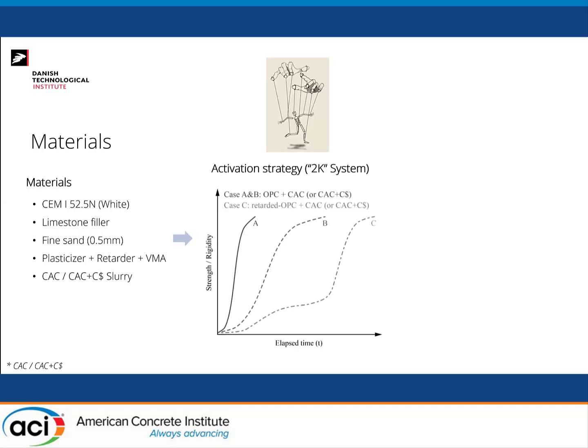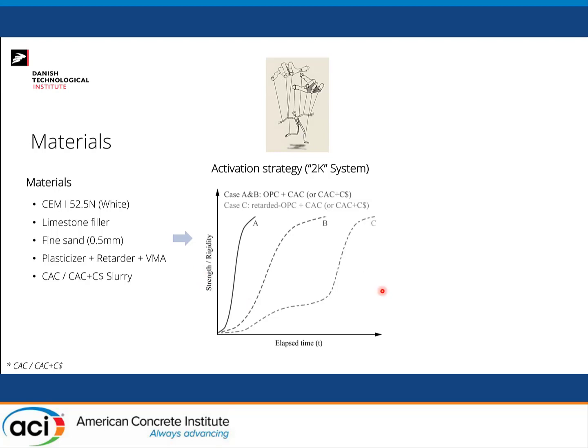So the strategy here I would describe as a 2K component. I have two systems that have to be added at a given rate in order to enable different scenarios that I'm showing in the graph at the bottom here. Let me see if I can put my pointer. Showing this chart at the bottom, how can you modulate the evolution of strength and rigidity, so structural buildup in general, by playing with these two ingredients? Of course, from the base mix, we can already modulate the open time of the mix by increasing the amount of retardant, and also guarantee that you don't have a high workability loss. And then the slope of the curve going up is when the slurry, the activating ingredient, comes in to wake up the system and enable stacking the layers.